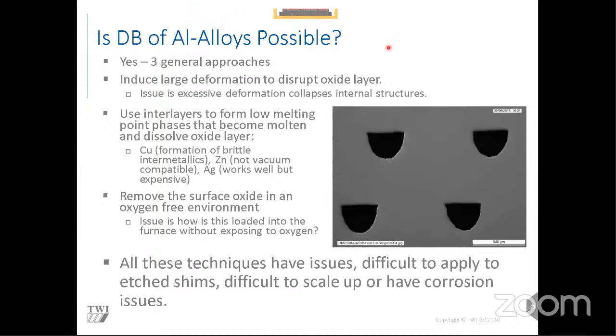So is it actually possible? And the good news is, yes, it is. There are 3 general approaches I will briefly discuss. The first is to apply a large load to induce large deformation into the sample - this will disrupt the oxide layer and allow diffusion between the different layers. The issue is, if you have intricate features, such as tiny channels, and you apply a load which is too high, they will deform into very thin crescent shapes and lose their functionality. So there's a limit to how far you can take this.